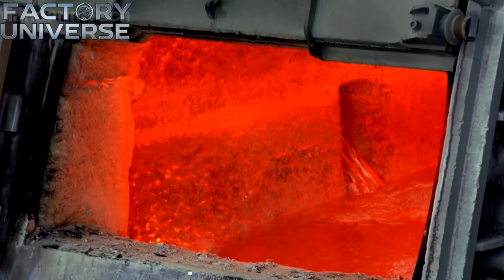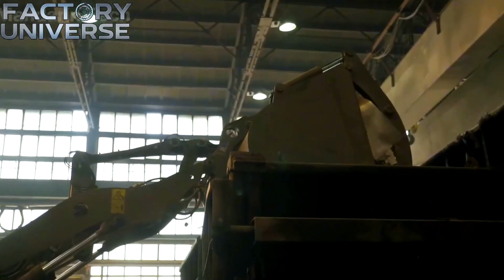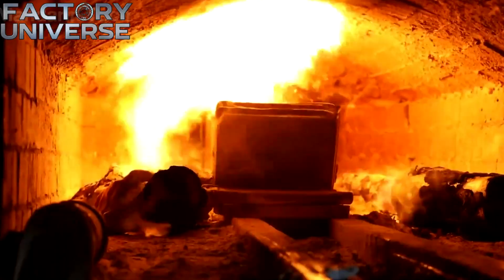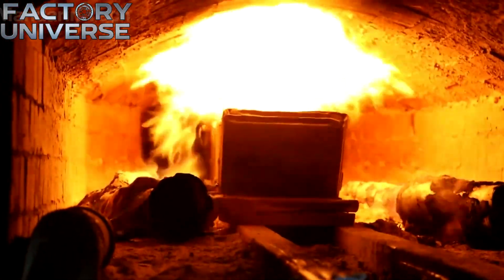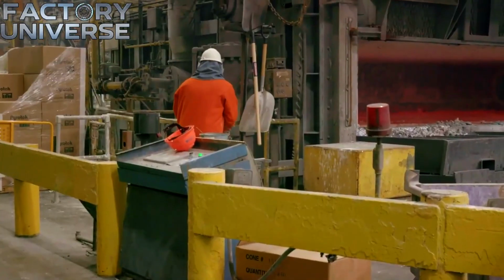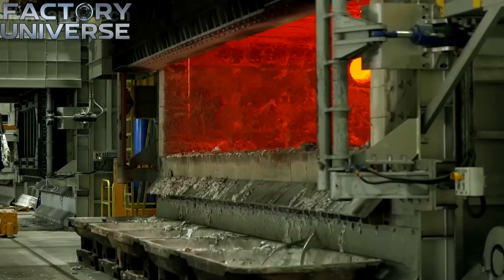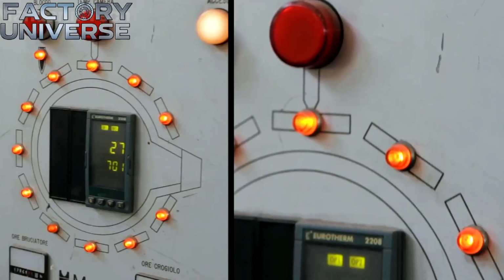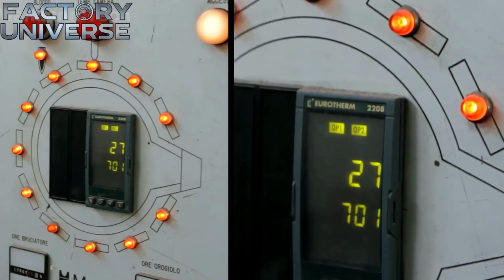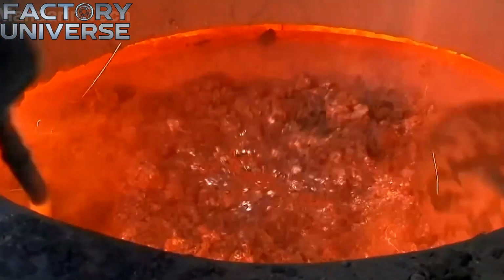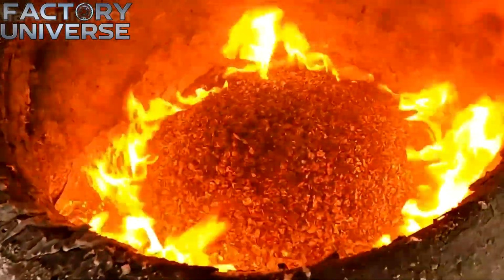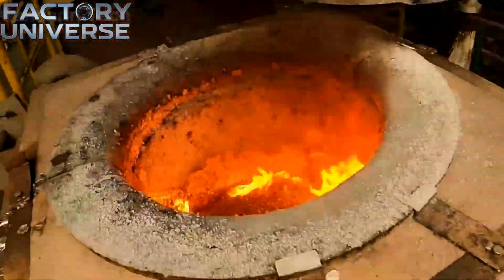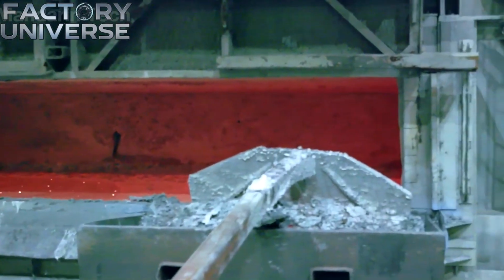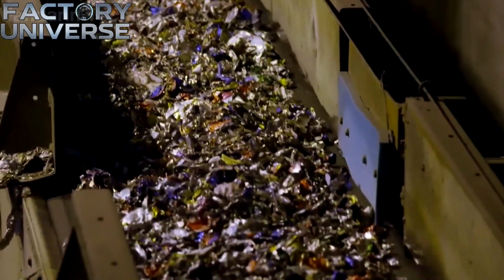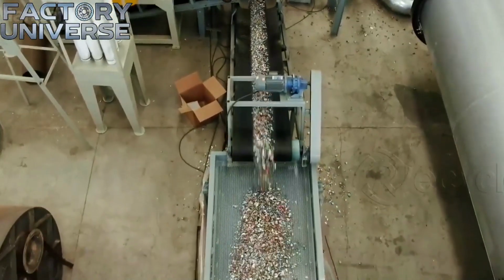660 to 750 degrees Celsius is the temperature range where aluminum scrap undergoes its final metamorphosis within the furnace. Why must the heat be maintained with such rigid precision? At first glance, melting metal seems like a straightforward thermal reaction, but in reality, the slightest deviation can cause the loss of critical alloying elements or allow the aluminum to oxidize into useless slag. The molten liquid remains inside these sealed systems where temperature, airflow, and the rate of material mixing are regulated simultaneously to ensure a perfect melt.